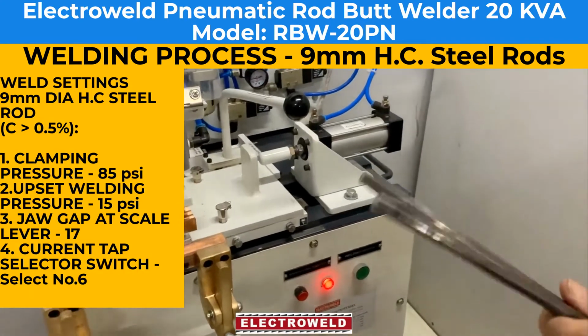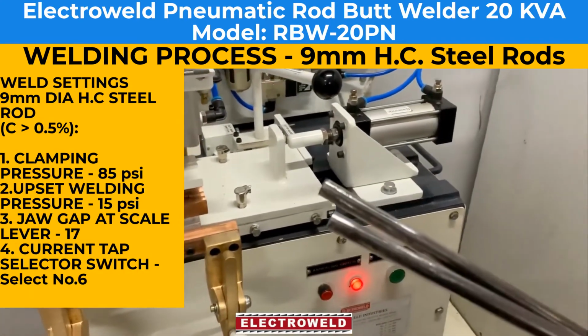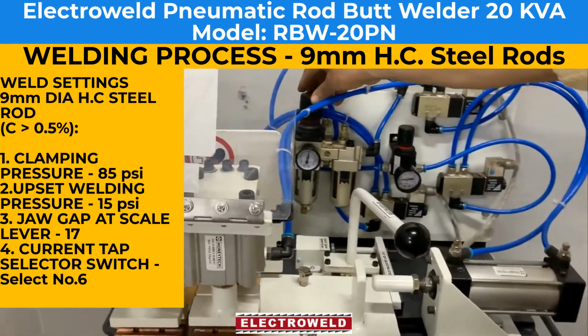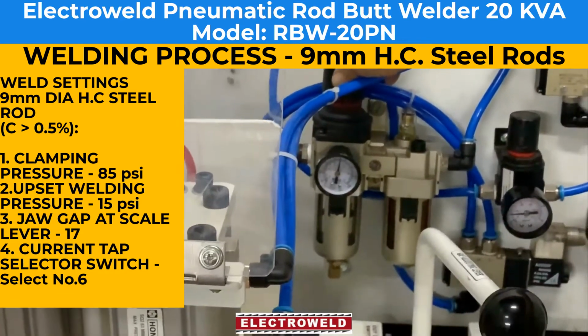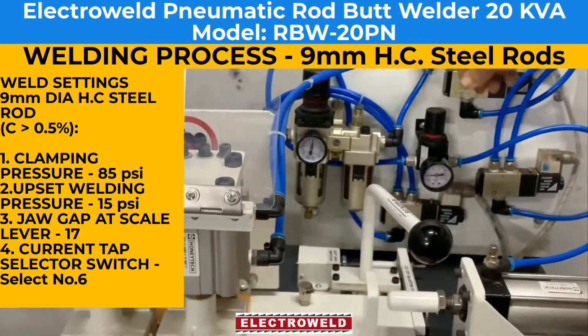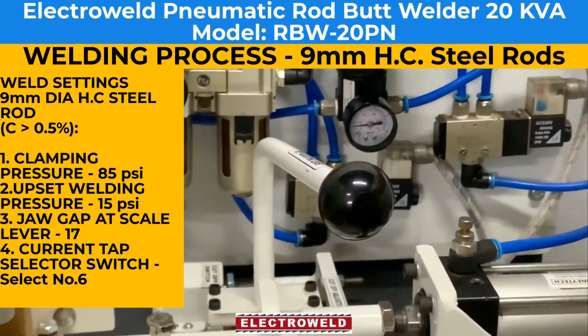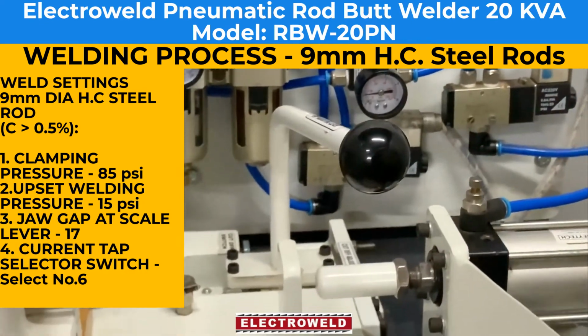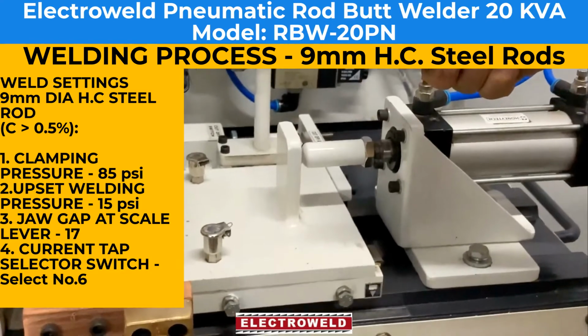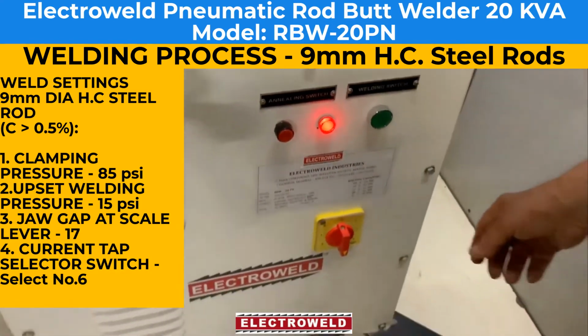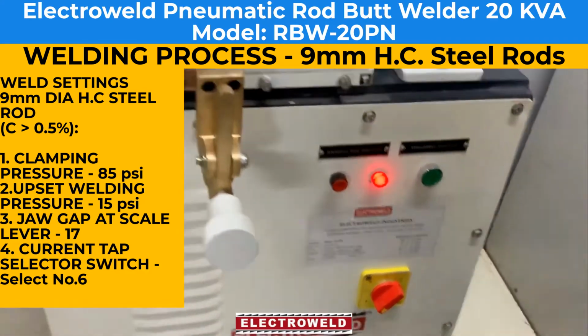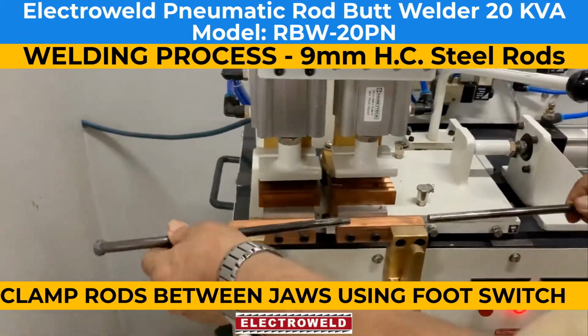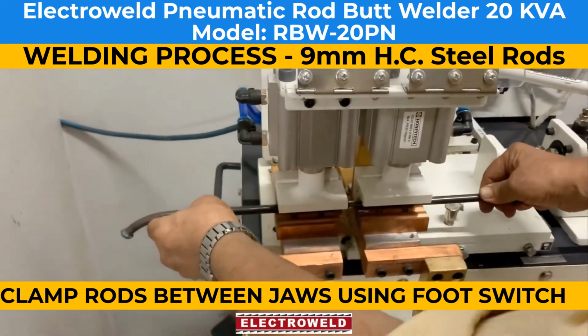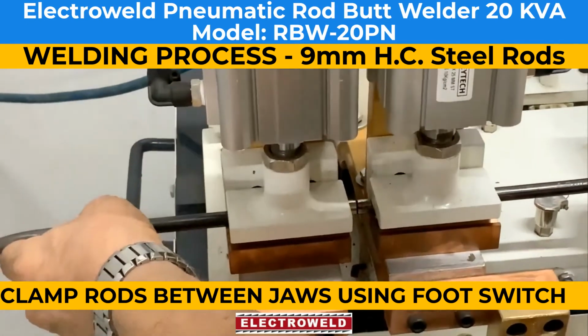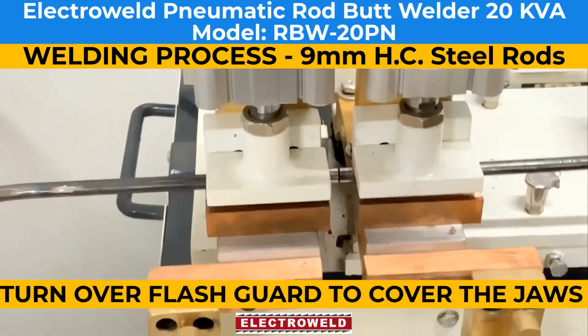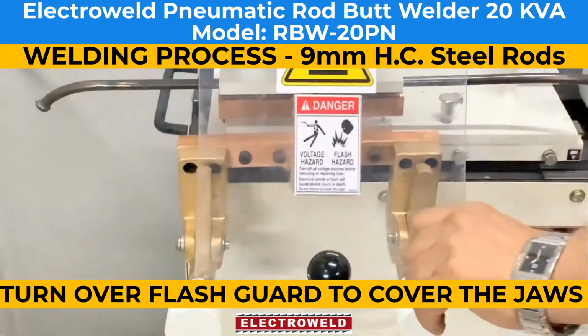The welding of 9 mm dia high carbon rods to be welded. For this, as per the data given in the manual, adjust the pressure to 85 psi for clamping. This welding pressure we adjust to say 15 psi. Then gap at scale keep at 17. Then current tap at number 6. Now we can clamp the rods to be welded in the welding jaws in the center. Then press the push button for welding. Before that we will put the flash guard on.